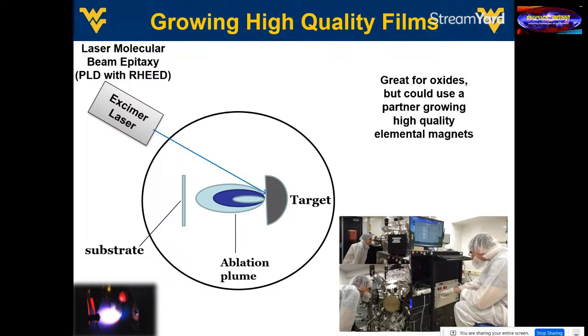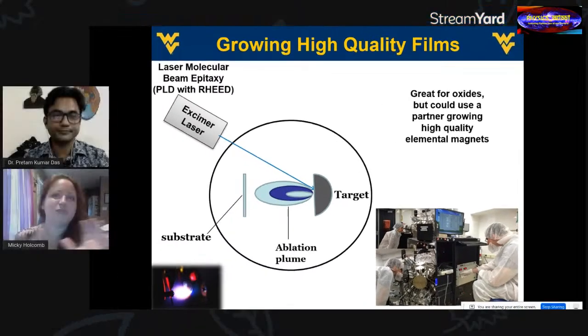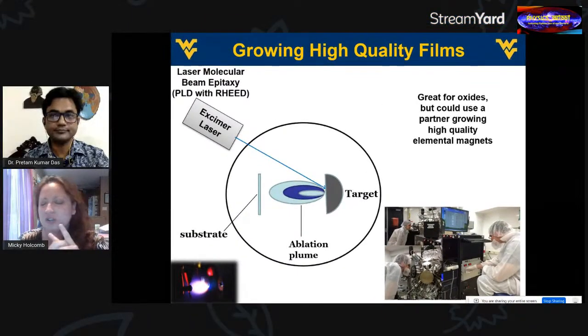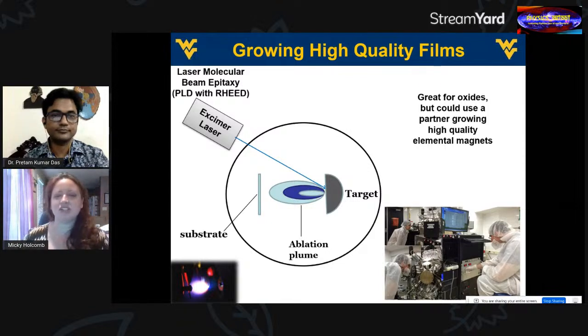But the nice thing about combining these two is it's really the best of both worlds. So MBE, molecular beam epitaxy, is a very expensive technique, both monetarily and time-wise. Pulse laser deposition, on the other hand, while it's not cheap, it's more expensive than sputtering, for example. You can do it relatively quickly, but when you add the RHEED system in, you can get very high quality materials. So this is kind of a schematic of how pulse laser deposition works.